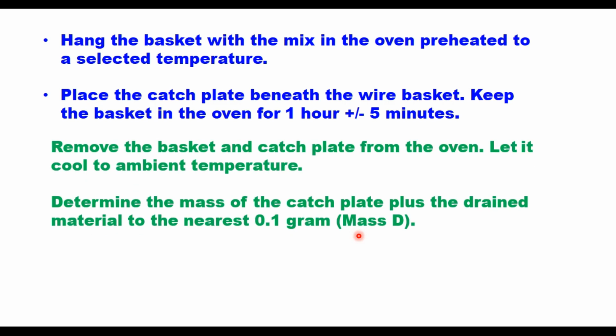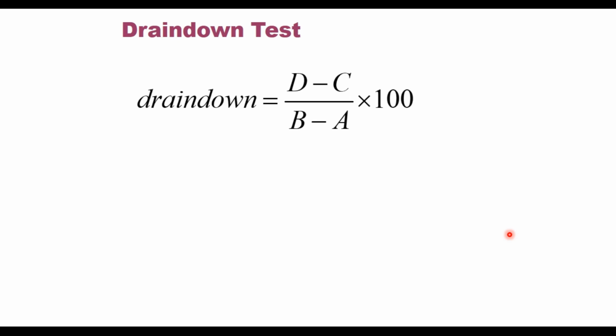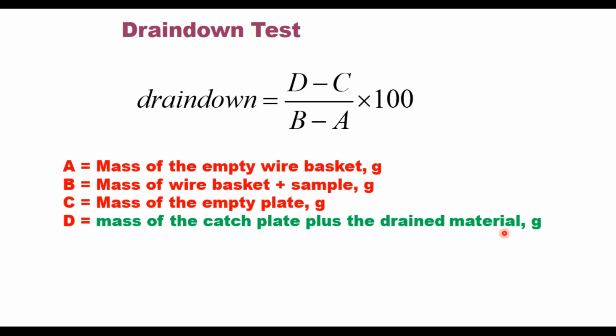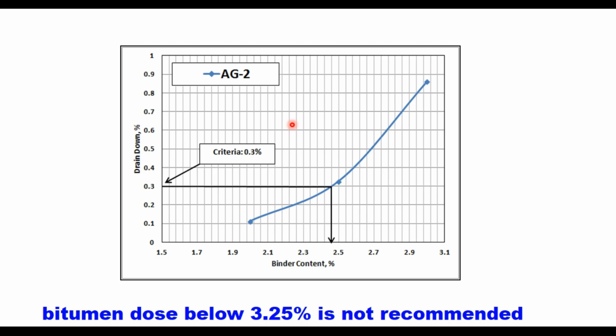After that, remove the basket and catch plate from the oven. Let it cool to ambient temperature, and then determine the mass of the catch plate plus the drained material to the nearest 0.1 gram, and let us say this weight is D. So drain down value is calculated by this equation, (D − C) / (B − A) × 100, where this D − C is the weight of the drained material, drained asphalt, and B − A is the sample taken initially. Drain down will increase with the bitumen content, and the limiting value here is 0.3.